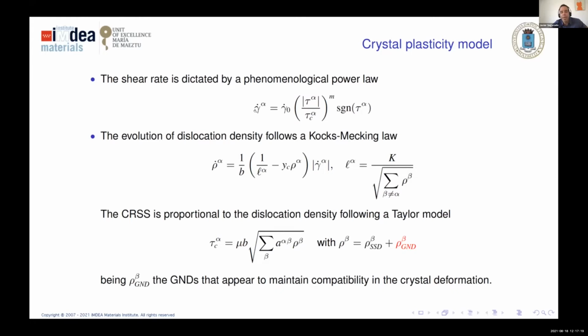The model is based on Kocks-Mecking, so we have an internal variable, the statistically stored dislocation density, which we call rho. Its evolution is driven by the Kocks-Mecking equation, which has a creation or accumulation term and an annihilation term. We have some parameters: K, which models the availability of the material to accumulate dislocations, and another that is the distance for annihilation.